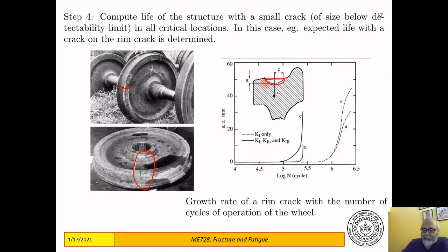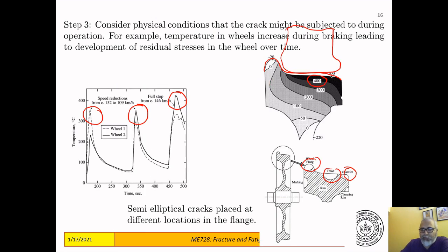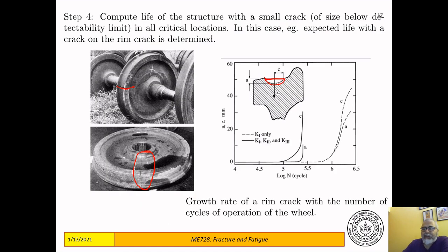So this is again a semi-elliptical crack from this location, which is called the tread location, which comes in contact with the rail and has a very high temperature. So you put in this temperature rise and the frequency of braking, etc., and then you try to see how this crack grows, and we come up with these kinds of diagrams.